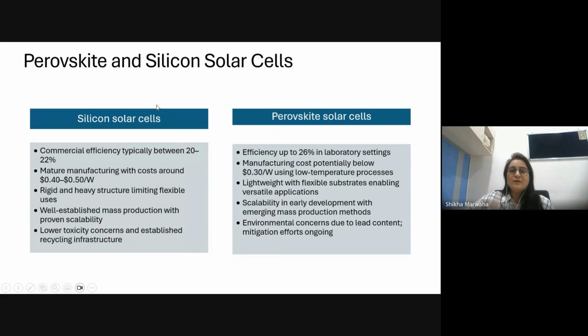So just to quote certain differences between the perovskite and the silicon. Silicon, as I have already said, the commercially available efficiency for crystalline silicon, or the silicon that we are using right now, is 20 to 22%. Because experimentally, although we can achieve 27, 28%, when it comes to getting this efficiency at commercial level, the total efficiency is near about 20 to 22%.